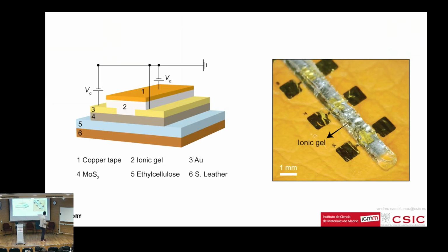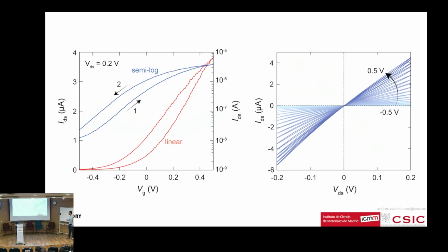Another example I wanted to show is that we can even fabricate, on these super rough surfaces, a field effect transistor. Making conformal field effect transistors is difficult because dielectrics are typically a problem for making good field effect transistors. One way around it is to use ionic gels. So we fabricated this molybdenum disulfide with ionic gel geometry, and it works like a charm. It works as a transistor, so you can switch the channel on and off.